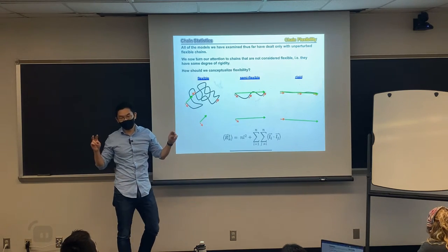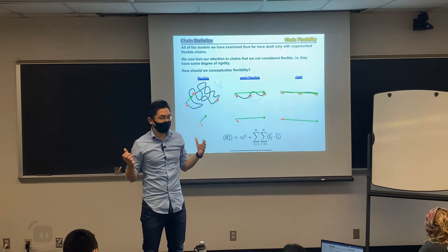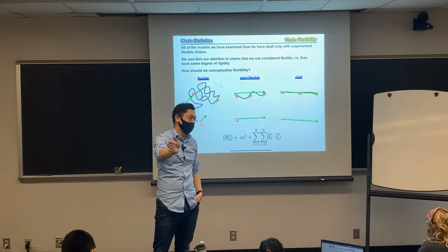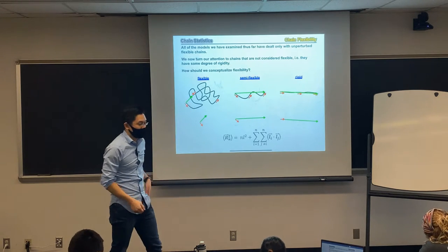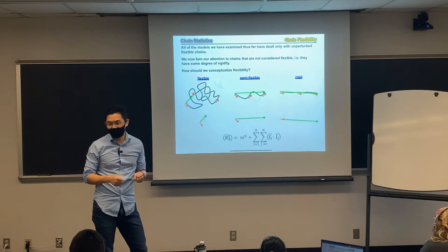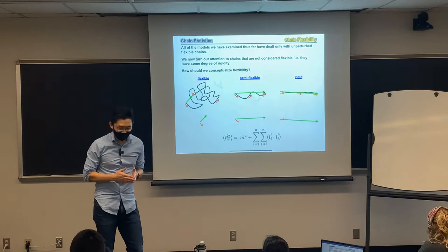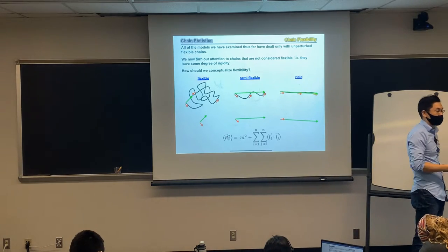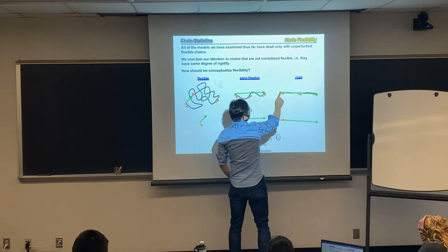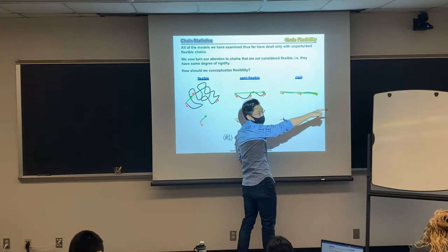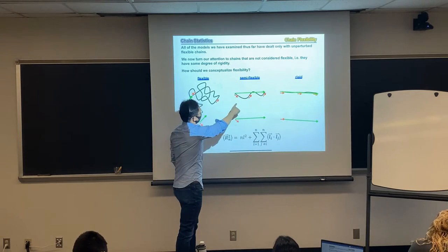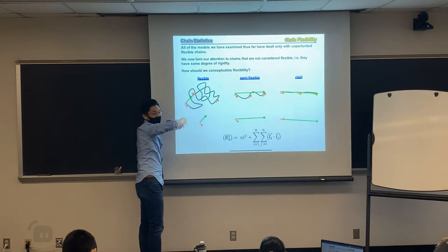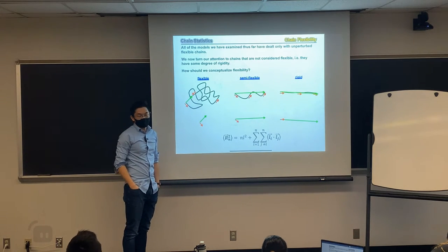There's two kinds of typical ways people define it. If you talk about how long it takes this polymer chain to bend by 90 degrees, in layman's terms, this is called persistence length. So how strongly this polymer wants to maintain its directionality, right? Directionality, which means which direction I'm going. So if I maintain it over a long distance, then I know this is very rigid. This one loses directionality more quickly than that one. The more quickly it turns, the less rigid. So that's a very good term to describe the rigidity of the polymer.